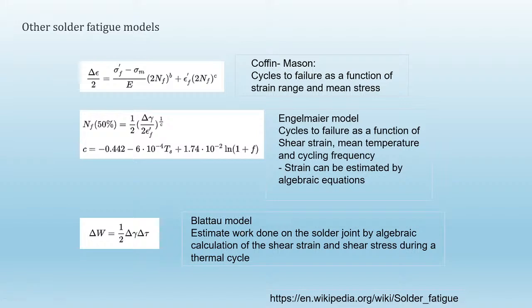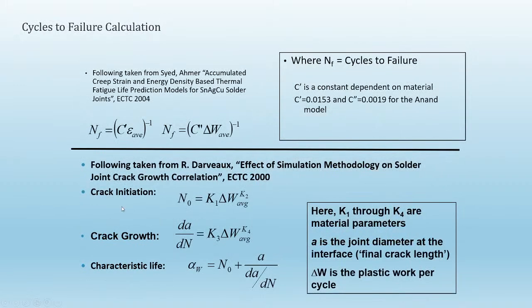Similarly, Dr. Blattau was part of DFR Solutions, which was acquired by Ansys recently. He was able to extend the Engelmaier model and fit it with Syed's estimates. So in addition to looking at just the shear strain, he was able to calculate using algebraic methods, based on the size of your package, the size of the solder, and the relative CTE mismatch, what the shear strain and shear stresses are through a thermal cycle. From that, we can calculate the amount of work done, and then plug that into this delta W here and try to get the same type of result.